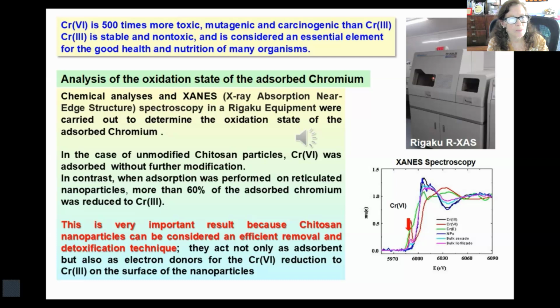chromium. This is a very important result because chitosan nanoparticles can be considered an efficient removal and detoxification technique. They act not only as adsorbent, but also as electron donors for hexavalent chromium reduction to trivalent chromium on the surface of the particles.